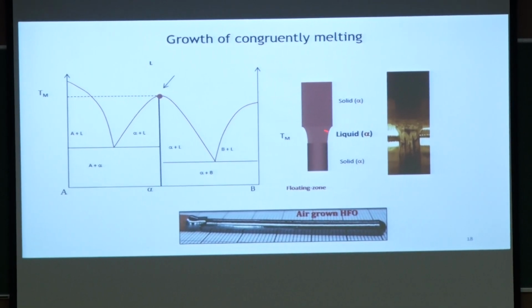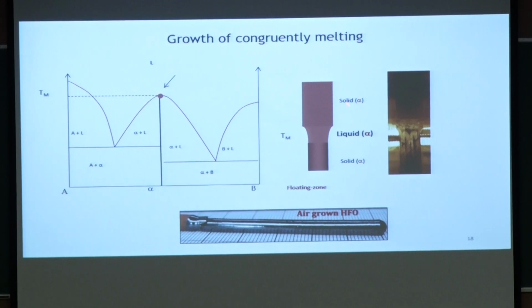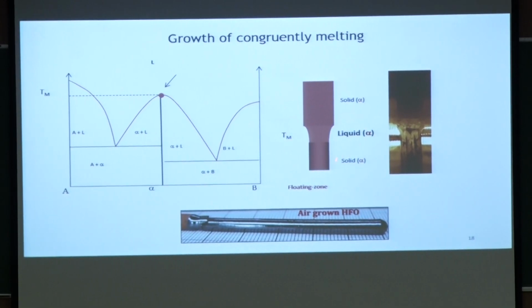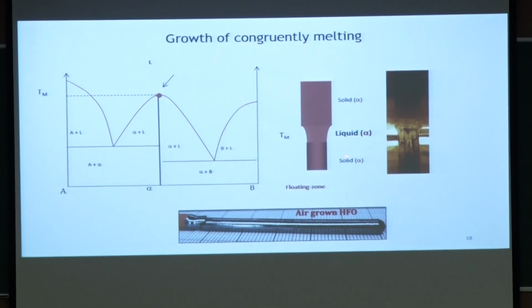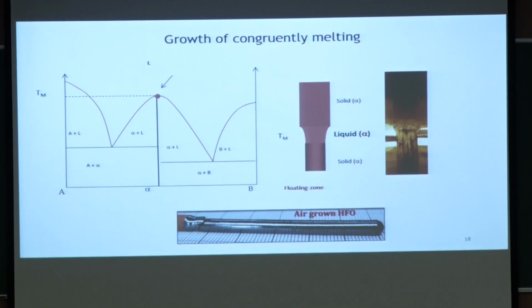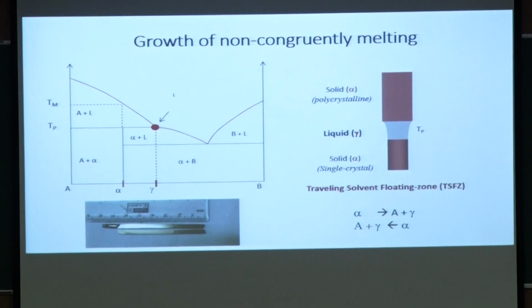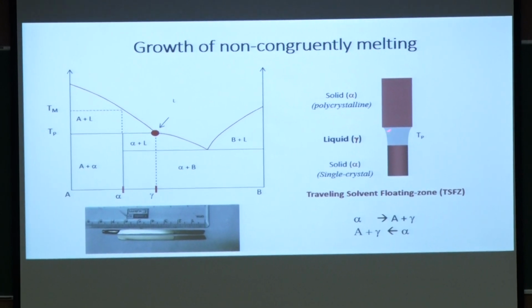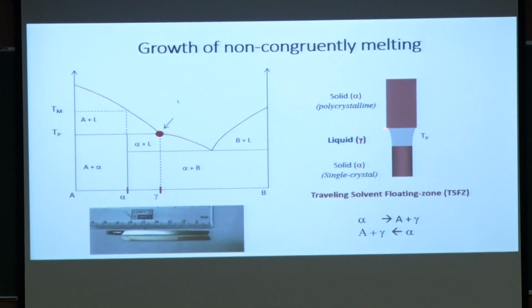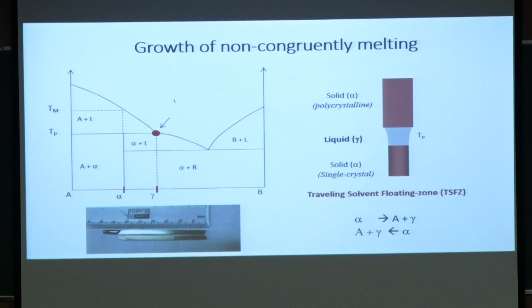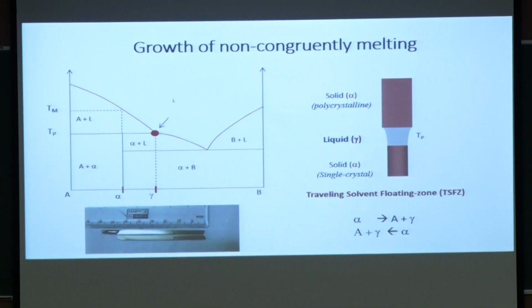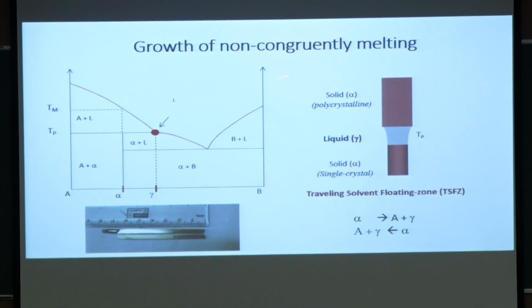This is the situation when the material melts congruently. In this case, the melt has the same composition as that of the compacted rod or the crystal that you are growing. So things are fine, alpha and alpha. But then it changes dramatically. Here you have alpha as the composition, and then gamma is the composition of the melt, and then you again get a crystal which has a composition alpha. So this is called non-congruently melting behavior.